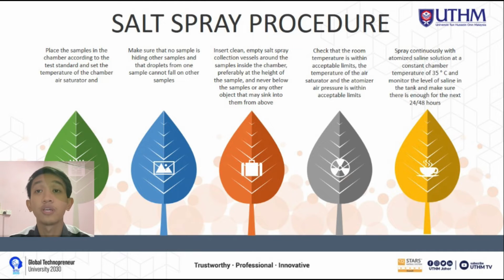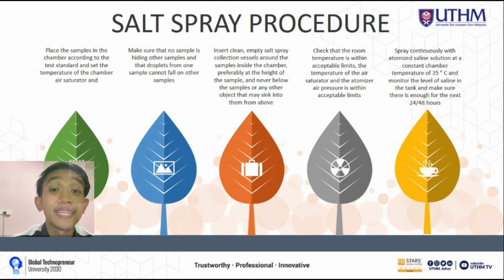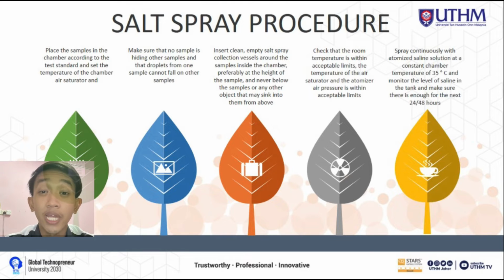Okay, next we are going to the salt spray procedure. Okay, first of all, the most important thing, we need to clean the surface of the material that is being inspected. Then the sample is placed in the chamber according to the standard, and the test chamber's temperature is set based on the test standard. Okay, then make sure no sample is hiding another sample, which can cause the droplet from one sample to fall on another sample.